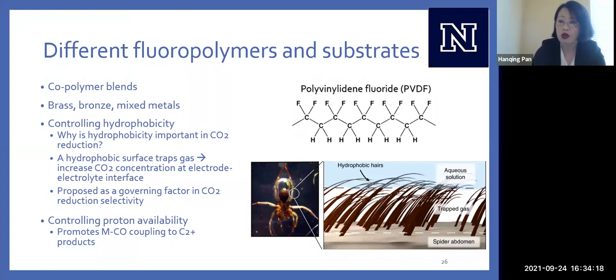One last thing we could do, we know that CO2 reduction reaction requires protons and electrons. And so we're doing our reaction in water, essentially. There's lots of protons there. But what if we can control proton availability? We've been able to control proton transfer rates with the Nafion membrane, the amount of shuttling of protons, but can we control proton availability? If we take away some of the proton concentration, instead of protonating that CO intermediate to generate methane, can we push these CO intermediates towards each other? So can they couple with each other to make multiple carbon products?